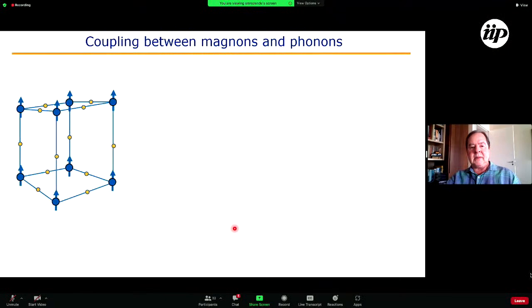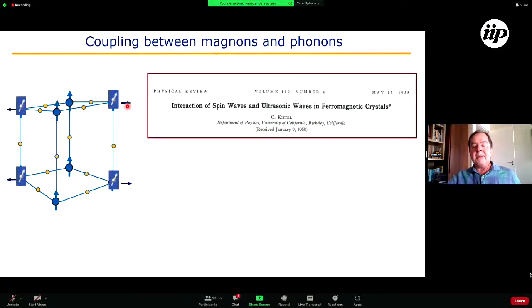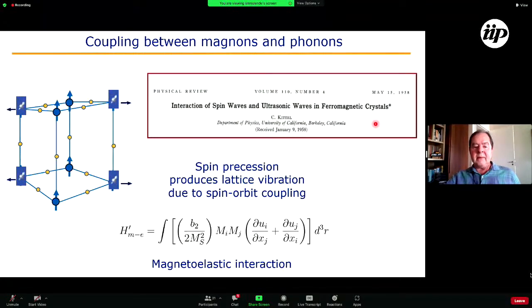Now, how come we can couple magnons to phonons? The reason is that if we have a magnetic material, here are the spins, and if the spins precess, because of the spin-orbit interaction, the precession of the spins couples with the lattice vibration. And the lattice vibrations are the phonons. And it turns out that 64 years ago, Charles Kittel, a brilliant theoretician and also a very good writer of books, as you know, proposed that there was an interaction between spin waves and ultrasonic waves in ferromagnetic crystals, and he proposed an expression for the magnetoelastic Hamiltonian.